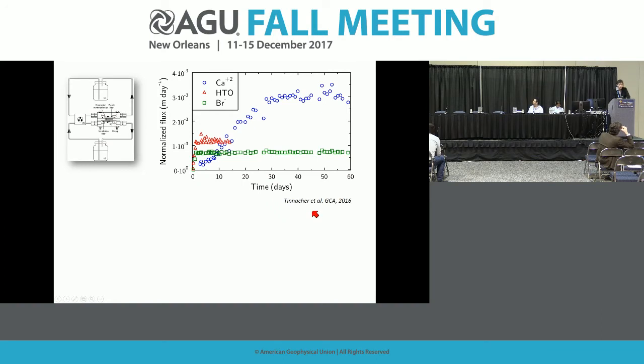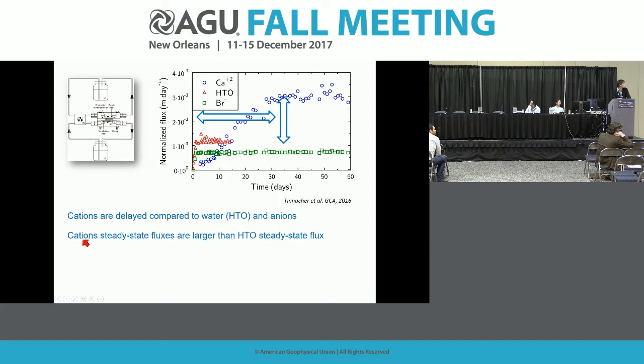If we look at the diffusion experiment that enables us to obtain some diffusion flux and so some diffusion parameters, here you can see a typical behavior of a clay sample. So you are looking at the flux as a function of the time, and after a transient state, you obtain a steady state. But you can see that if you look at cations compared to H2O or to anions, you have cations that are delayed compared to H2O and anions. You have cation steady-state flux that is larger than H2O steady-state flux, and you have anion steady-state flux that is lower than H2O steady-state flux.